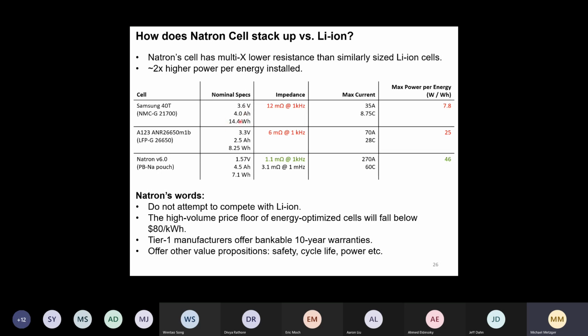So we see the energy of the NMC graphite cell is highest, then we have the LFP cell, and for these Natron cells, due to this low operating voltage, we pay quite an energy penalty, but the cell resistance measured here by impedance spectroscopy at a certain frequency is factor 10, factor 6 roughly lower than NMC and LFP cells. So we already saw you can charge or discharge these cells with a really high current, a really high C rate.